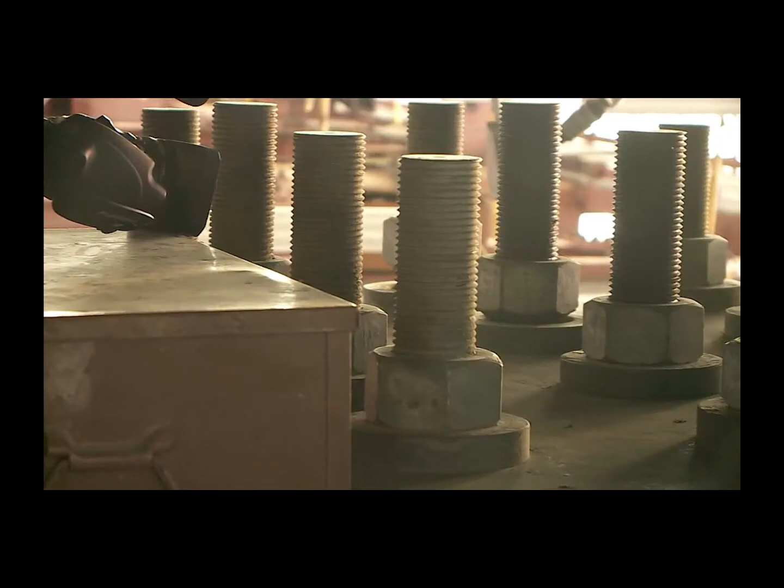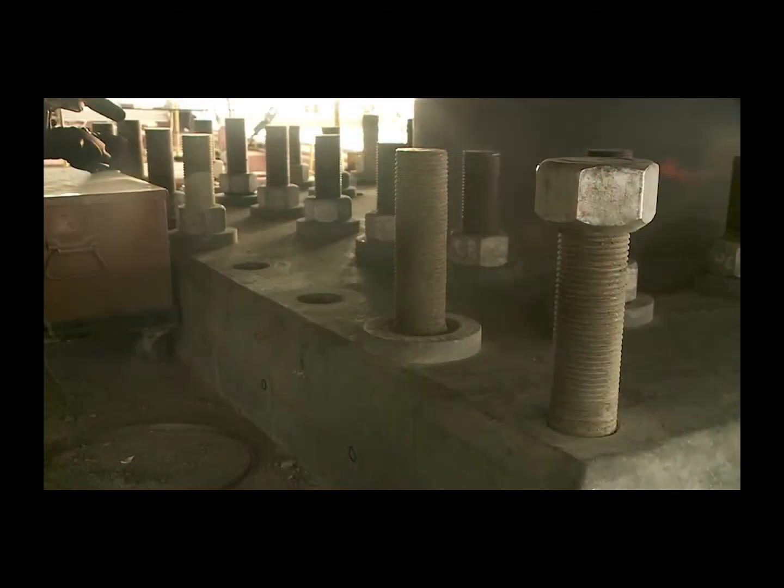The materials that were used in these bolts were not the appropriate material to use. UC Berkeley metallurgist Thomas Devine says bridge designers made several mistakes. First, they ordered bolts that were too hard on the outside, making them susceptible to hydrogen cracking. Then they galvanized the bolts, leaving them even more vulnerable to hydrogen. And finally, they installed the bolts without enough testing.